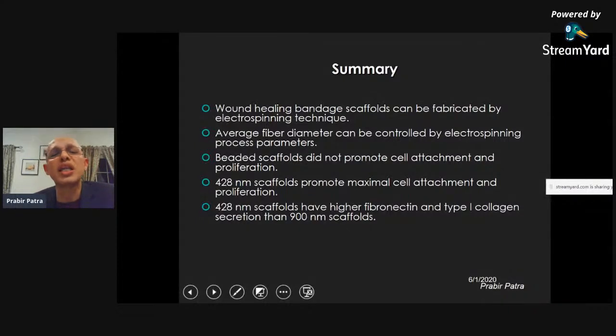So on this, I'll go quickly through a summary of this particular observation. In this case, we used an FDA-approved polymer called PCL, polycaprolactone. That is our scaffold. We used skin cells to grow on it. And we found out by playing with all the parameters and using the electrospinning process, we can form a scaffold that at 400 nanometers and smaller can grow skin cells very well. They grow, they attach, they proliferate, and they form into tissues.